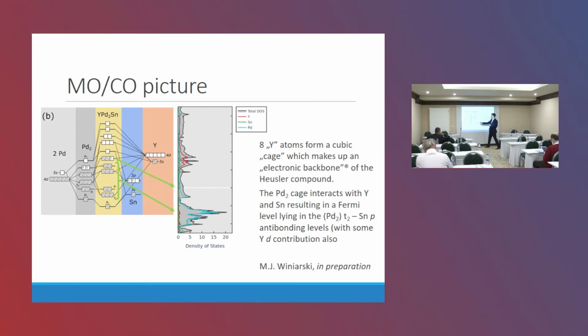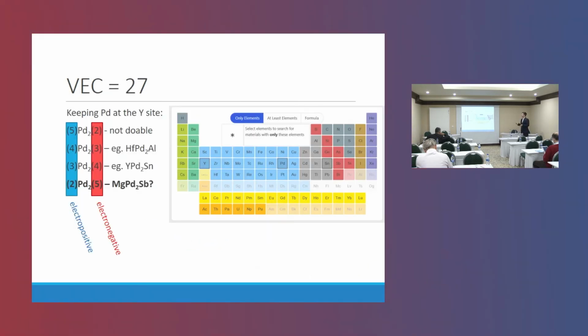It has eight yttrium atoms forming a cage, which interacts with palladium and tin, forming an anti-bonding Pd2Sn state at the Fermi level. Okay, so if we take the magical 27 electrons as our selection criterion, what new compounds can we find this way?